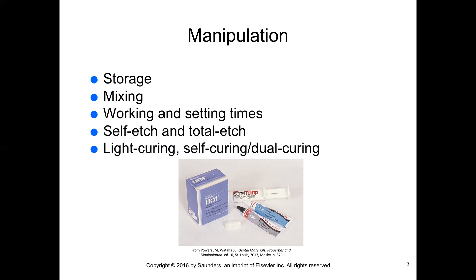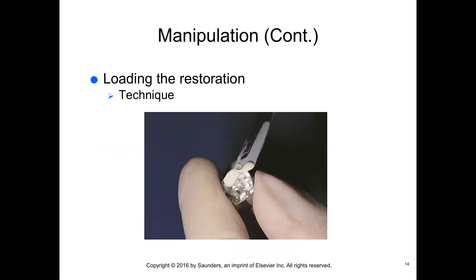Materials that are bonded in place require the additional step of etching to achieve good bond strength. The setting of cements may be initiated by three means: self-cure, light cure, or a combination of both called dual curing. The dental assistant may be responsible for filling the crown with luting or bonding cement before passing it to the dentist. Once mixed, the cement should be gathered at one location with the spatula, the blade wiped against the margin of the restoration, and the walls covered with a thin, even coating. This figure shows loading of a crown — you wipe the spatula blade against the crown margin to deposit the cement, then use the tip to move it around inside the crown.